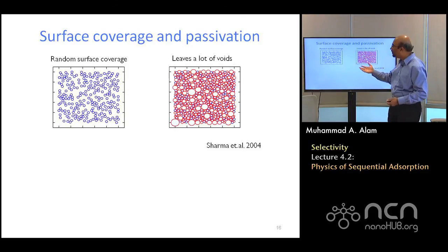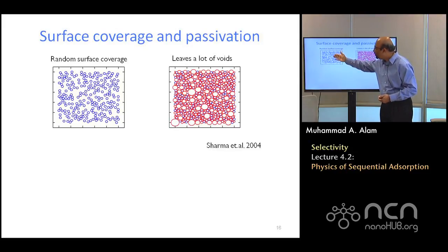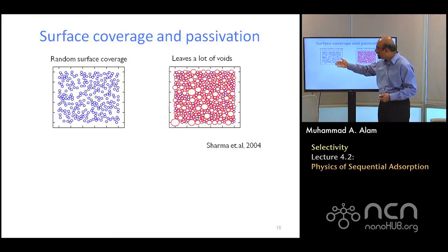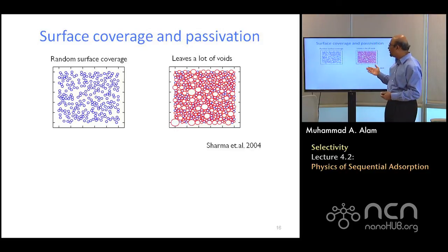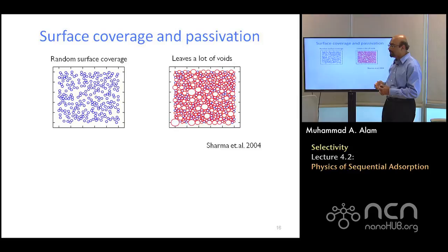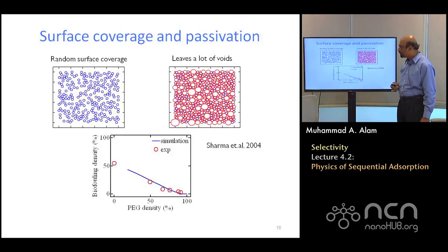It's simply saying what fraction of the area is empty. And at saturation, 54% would be occupied by the blue, and the remaining would be empty. But we have not gone to full saturation yet. At full saturation, the gap would be no bigger than individual biomolecules. And at full saturation, therefore, things would be considerably better. But we are not there yet, and you can see large empty spaces in various places.